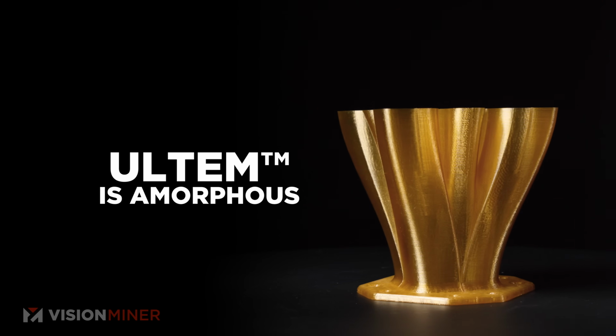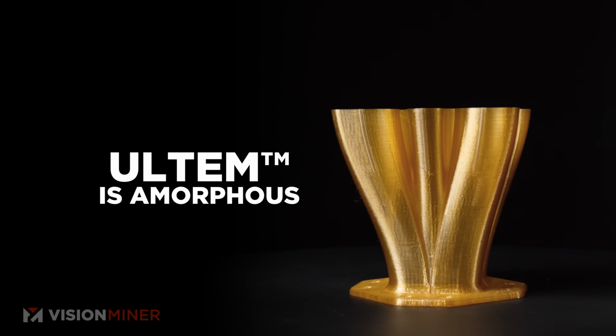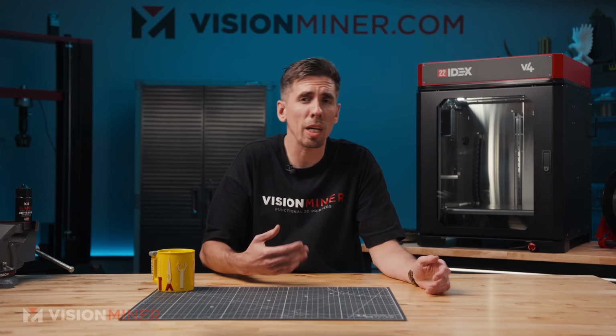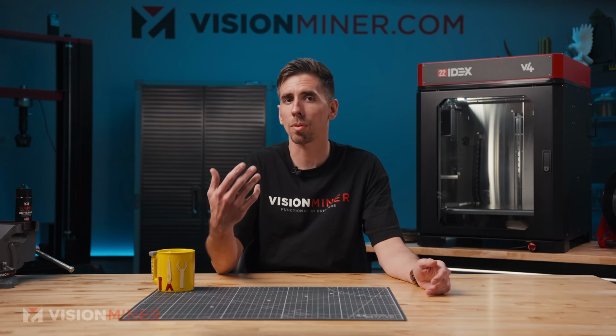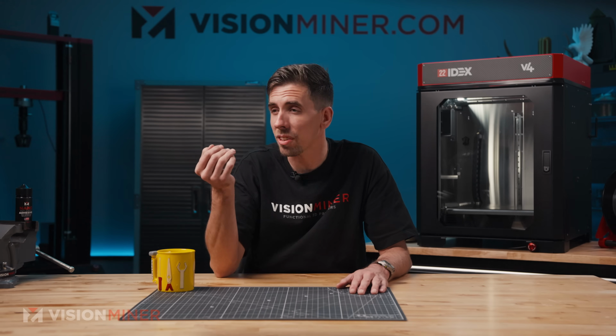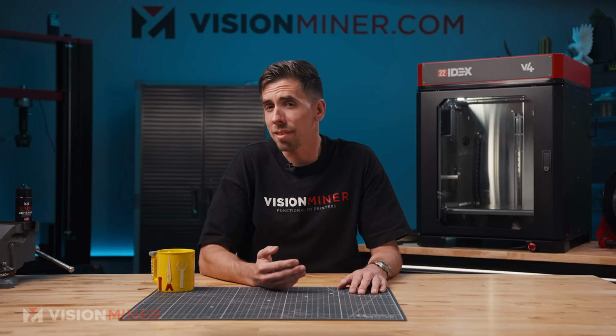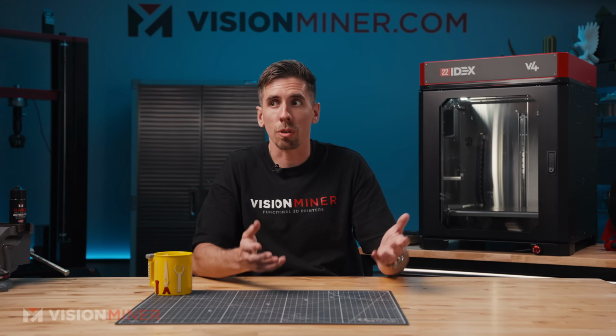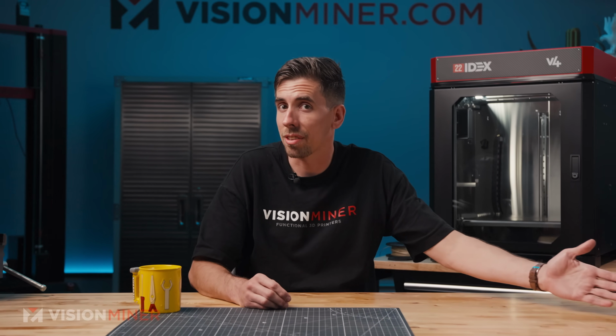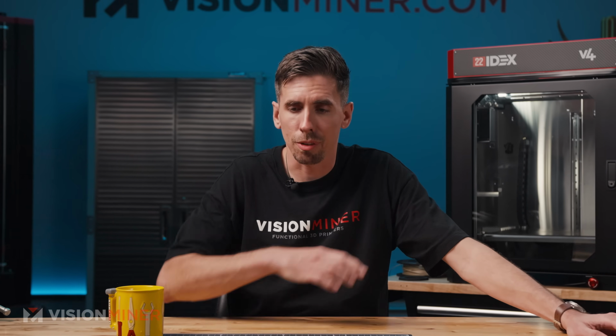ULTEM, though, is different in three critical ways. First, it's amorphous, so there's no crystallization, which sounds like a good thing. It also means that stress doesn't relax out the way it does in semicrystalline materials. As an ULTEM part cools from about 350 to 380 Celsius down to room temperature, the internal stress basically gets frozen in. That's when you get delamination between layers. You get microcracks that sometimes don't appear for days until later. You get warping that'll snap thin sections and thin walls in half.